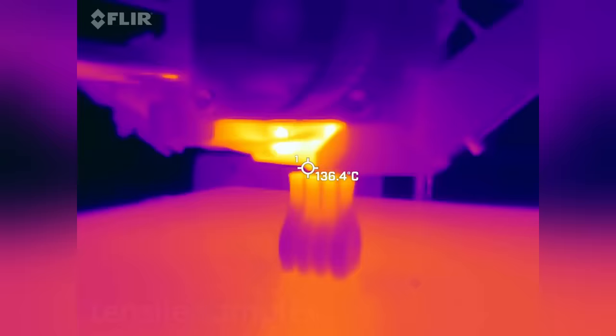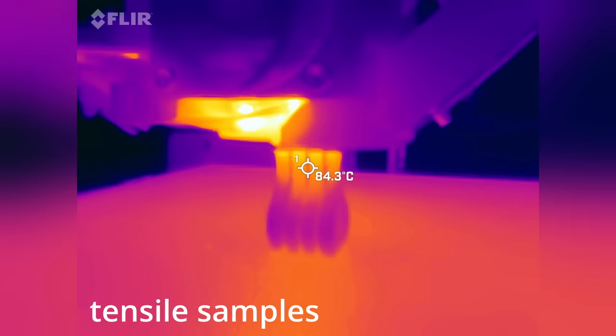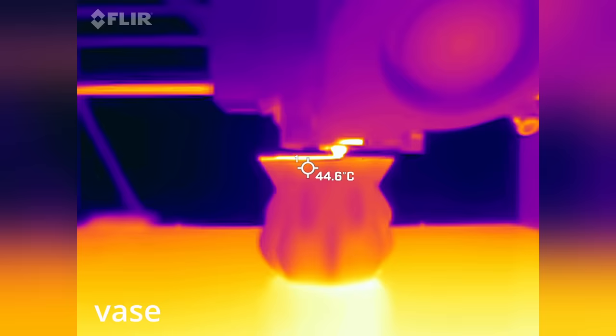The thin structures on the tensile samples with the low amount of cooling stay hot for quite a while and therefore gives the material time to crystallize. This, of course, depends on the shape of the part and the print settings.